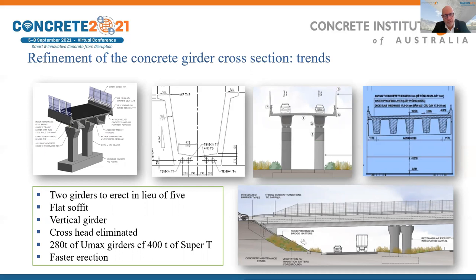The precast forming for the deck using Transfloor. You can see a substantial simplification of the substructure there. The fact that we only need two girders instead of five means we need fewer bearings, and indeed the soffit of that U is flat, not sloping as per the Super T, and so there's an inherent stability with the UMAX girders that just isn't there with Super T's. And really telling is the fact that we actually stretched these up to 42 metres.